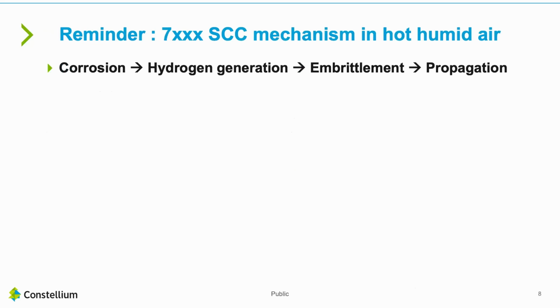So, a reminder of the general description of what happens during corrosion in 7,000 series in hot humid air. Corrosion may enhance hydrogen generation that will permit hydrogen to penetrate the metal, and then it can go to grain boundaries, create embrittlement, and then there is a propagation of crack due to both hydrogen embrittlement and corrosion.